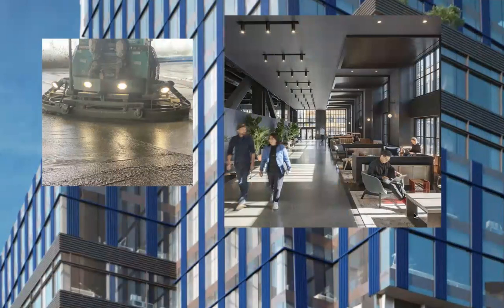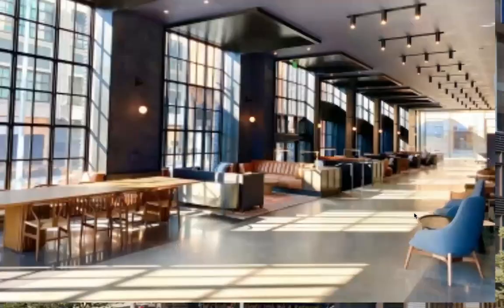This caused a big stink on a couple of social media platforms a couple of weeks ago. My belief is that if you're dry grinding, you've got to use a grout coat — you've got to fill those pinholes because you're not turning that cream back into a slurry; you're not making the concrete back into a plastic state. Because of that, you have to use some sort of a coating. So my argument was: if you're coating the floor, that makes it a coating — regardless if that coating is blue or clear or red. Here at this project we used a wet grind scenario, wet polishing. Turned out pretty cool.